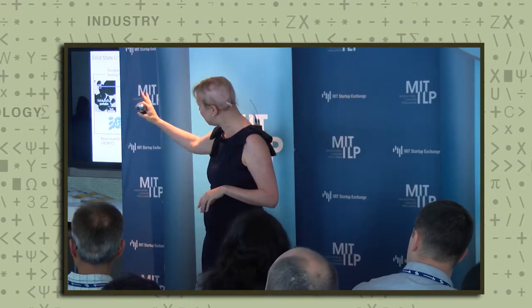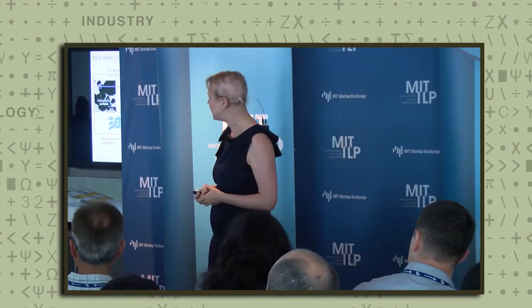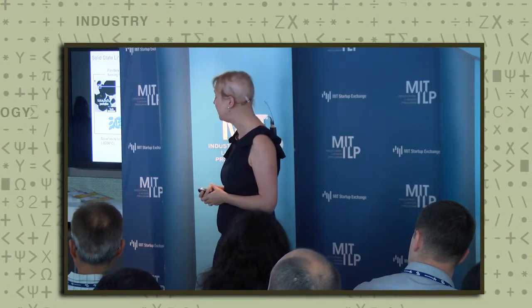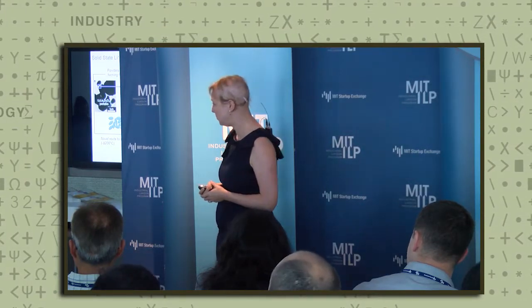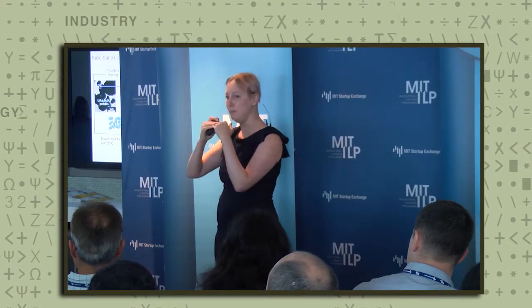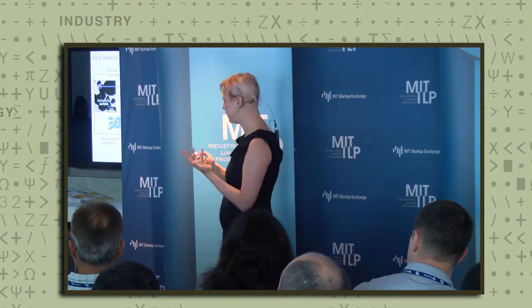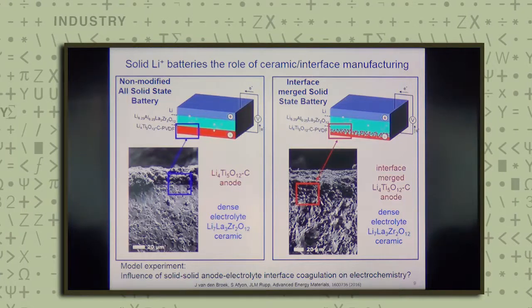And we can see here how that looks like. So this is now a lithium garnet ceramic electrolyte structure that is stable already at 950 degrees C, sintered to ceramics, and where we can start now to compose on top of that various electrodes that I will show you in the next slide. So here's two examples.